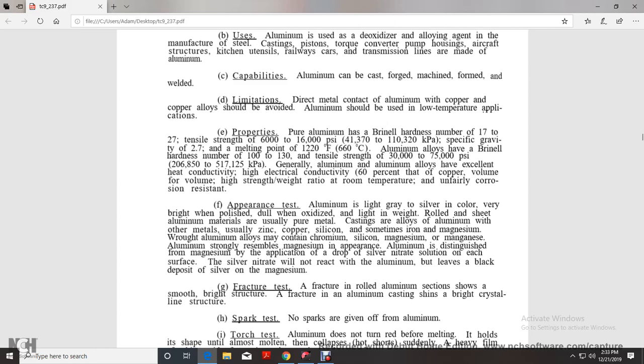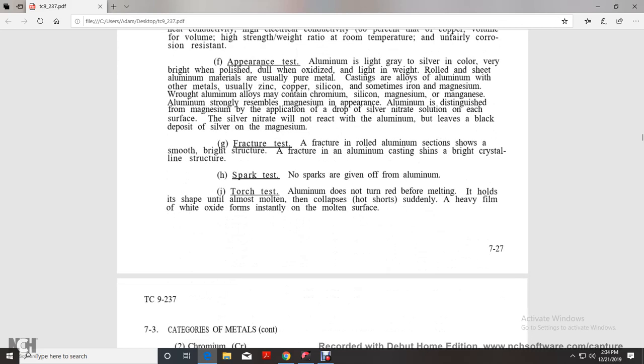Aluminum is distinguished from magnesium by application of a drop of silver nitrate solution on each surface. Silver nitrate will not react with the aluminum but leaves black deposits of silver on the magnesium. Fracture test: the fractured rolled aluminum section shows a smooth, bright structure. Fractured aluminum casting shows a bright crystalline structure.